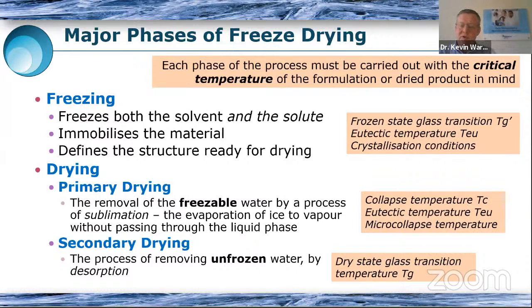And here in secondary drying, even though we've removed all the ice, it doesn't mean that it's safe to go maybe rapidly to room temperature or elevated temperatures and then take the material out of the freeze dryer straight away. We might need to be careful about how quickly or slowly we raise the temperature. And here we'll be mindful of what we call the dry state glass transition temperature, and that's called Tg. So you might notice that the frozen state glass transition is Tg prime, and the dry state glass transition is Tg. And these are things that we can characterize using some of the methods that we have available.